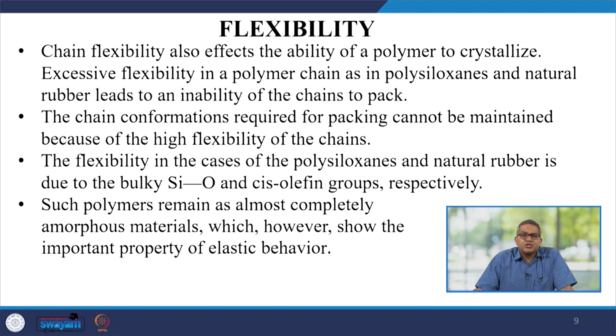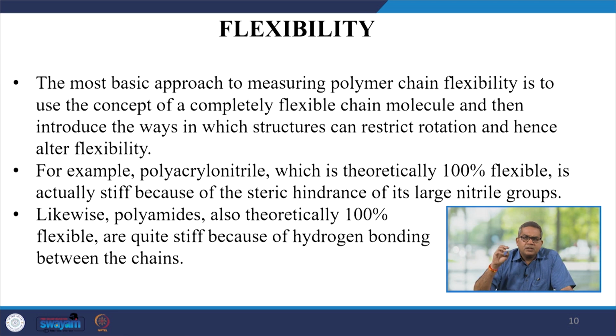The chain flexibility affects the ability of a polymer to crystallize. Excessive flexibility in a polymer chain, as in the polysiloxanes and natural rubber, leads to an inability of the chains to pack. The chain conformation may require a packing which cannot be maintained because of the high flexibility of the chains. The most basic approach of measuring the polymer chain flexibility is to use the concept of a completely flexible chain molecule, then introduce the way in which the structure can restrict the rotation, hence altering flexibility.